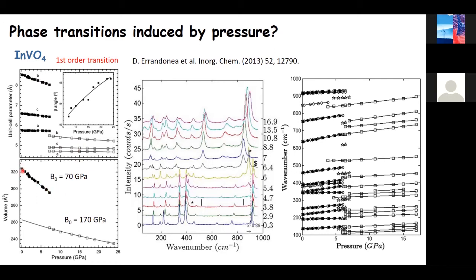One, the bulk modulus of the low pressure phase is 70 GPa, which makes indium vanadate the most compressible vanadate studied until now. This is reasonable because the crystal structure of indium vanadate is very open. When we have the phase transition, we have a large volume collapse. The volume decreases a lot, like 20%. The high pressure phase becomes much more dense, and therefore is much less compressible, with a bulk modulus of 170 GPa.